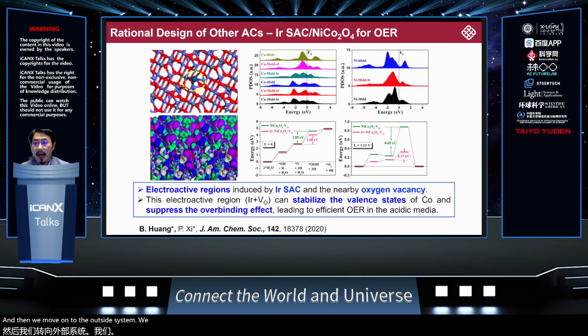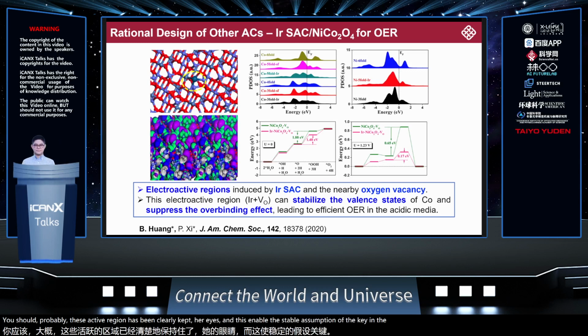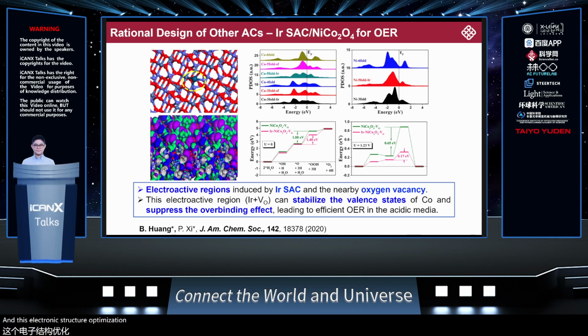We stabilize the iridium single atom coupling the oxygen vacancy on the spinel oxide through the experiment. Due to the coupling, this electroactive region has been clearly characterized, and this enables the stable absorption of the key intermediates and maintains the valence states of the surface cobalt sites. And this electronic structure optimization guarantees the efficient oxygen evolution reaction in acidic media.